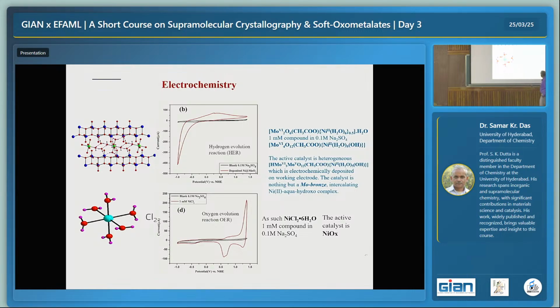This compound, if you take CV, you get this feature, one red feature, and after some time you get deposition. It is water soluble. But if you do electrochemistry for several cycles, you get deposition on the electrode and this gives water oxidation. After some time, oxygen stops because those particles agglomerate, then no catalysis.